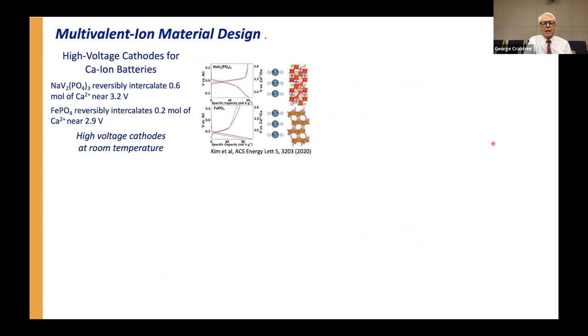With multivalent, the trick is, unfortunately, for calcium and magnesium and zinc and so on, none of the electrolytes and none of the cathodes that work for lithium ion will work for these multivalent materials. So it's a matter of rediscovering almost everything. They all exploit a pure metal anode. So it would be magnesium, calcium, or zinc as a pure metal. But the question is the electrolyte and the cathode.